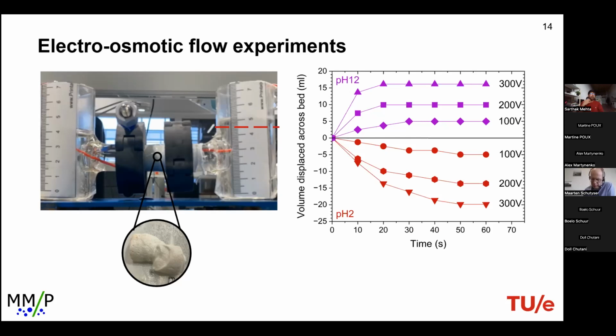So if you want an end game application for this, I genuinely see that this could, if you know how paper industry works, we use this conveyor belt system that consists of several rollers, and you heat up these rollers to then dewater or dry your paper as it passes through the conveyor belt. Now imagine, instead of using heat as a way to evaporate, these conveyor belts are made of electrodes, charged electrodes. So as you pass the slurry or sludge through this conveyor belt in between these two electrodes, and you apply an electric field, you can drip off water, specifically targeting water and not the biomass. So your energy is conserved because you're only using the energy to move water, and at the same time your dewatering is sustainable. So that's how I see it being used as an end case application for conveyor belt drying.